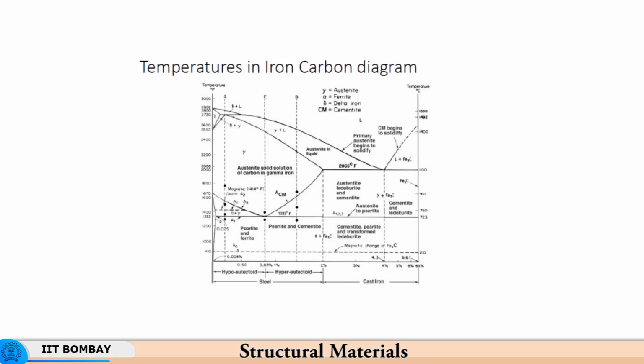As it cools down, you have liquid plus austenite getting formed. This gamma refers to austenite. So, slowly it cools, and then so this is the liquidus line, this is the solidus line, and then it has cooled below the solidus. So, it becomes entirely gamma, and so this is the austenite phase. It is a single phase.